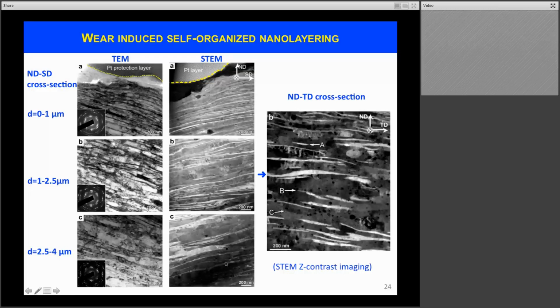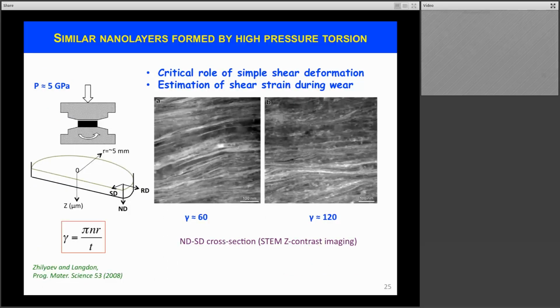And as we go deeper and deeper into the material, it is interesting and useful because essentially we are looking at this nanolayering reaction at earlier and earlier times, in the sense that the strain that has been applied here is small, and so the layering reaction has not had the full time to complete. This layering takes place along the sliding direction, but also along the transverse direction, as illustrated on this picture on the right. We also tested that this nanolayering reaction can take place under other types of severe plastic deformation, here high pressure torsion, where again simple shear deformation dominates.